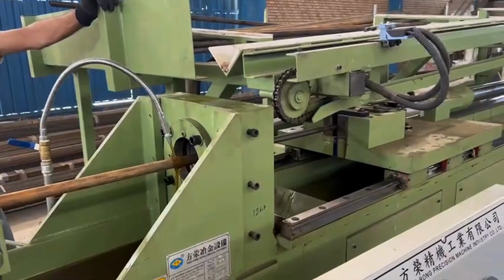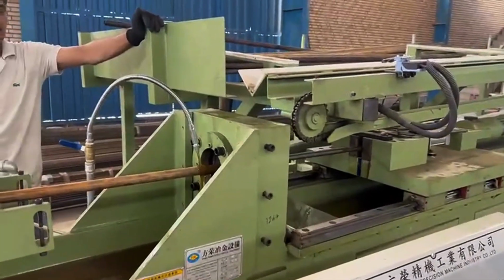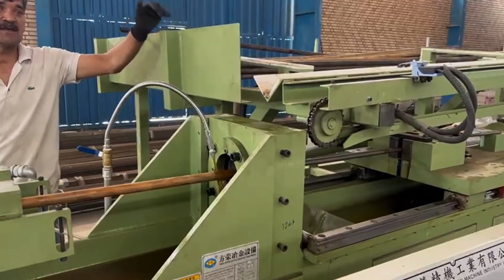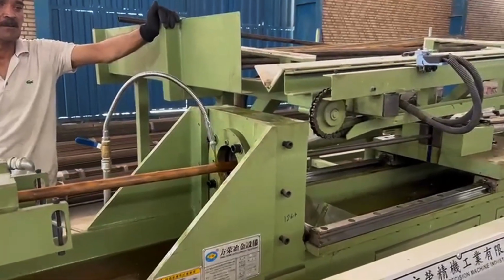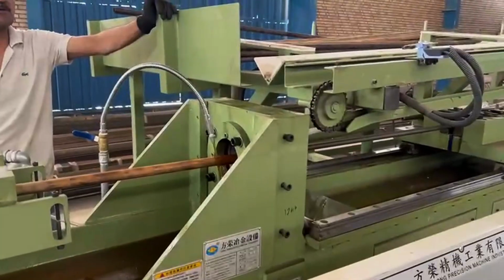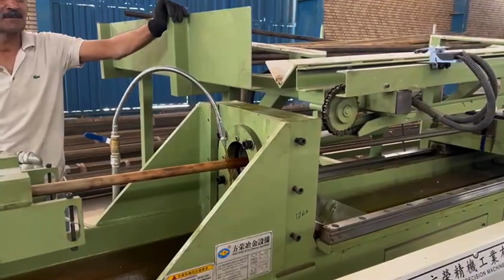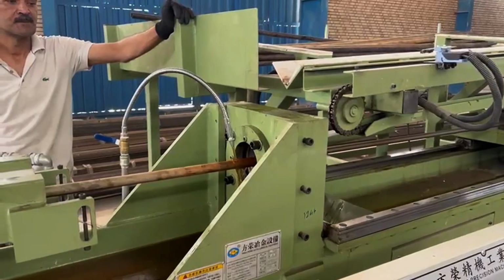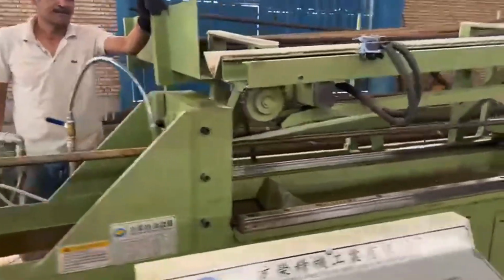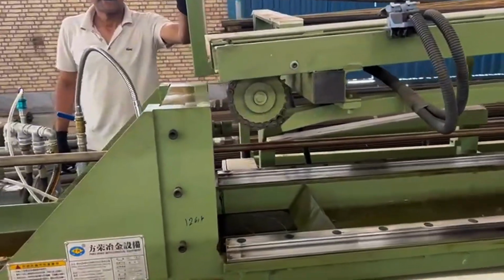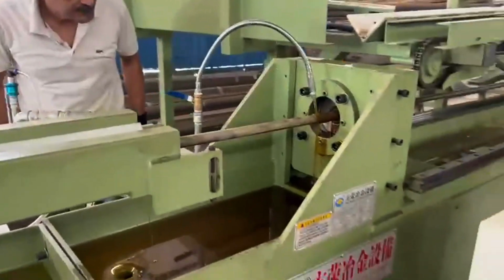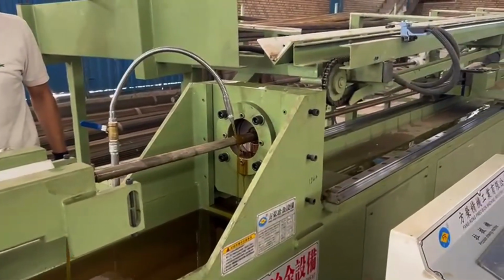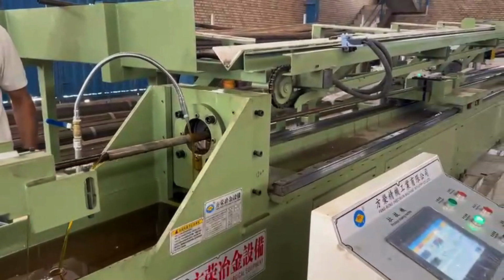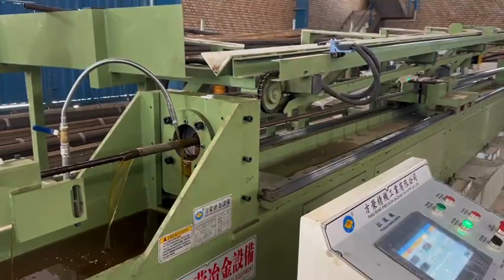Advantages over hot rolling. Compared to hot rolling, cold drawing offers: first, better surface finish, no scale, no oxidation. Second, tighter tolerance, often within minus and plus 0.05 millimeters. Third, increased mechanical strength by 20% to 30% due to work hardening. Fourth, no decarburization. Surface hardness remains high. Fifth, cost effective for small to medium batches. Quick die changeovers. The trade-off: higher pulling force and the need for intermediate annealing if you need multiple reduction passes.